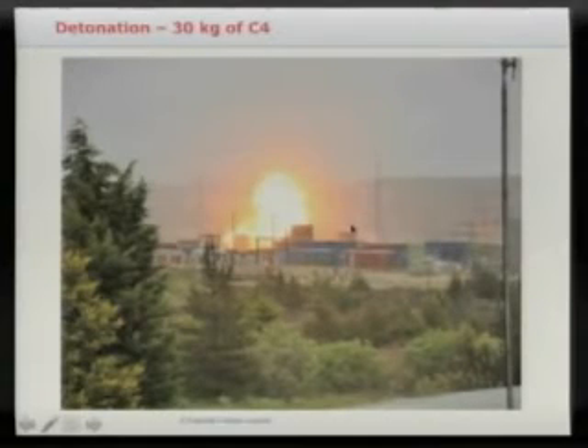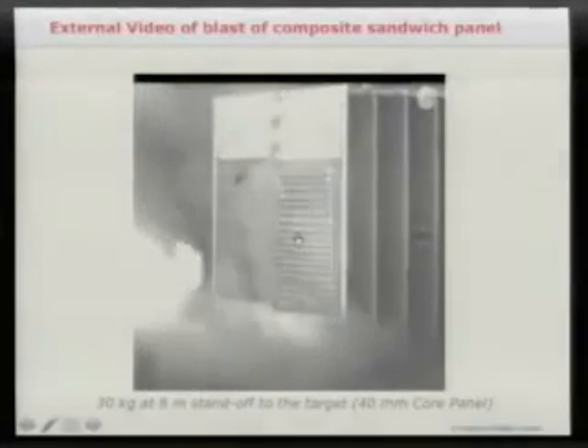So that's the charge going off from a safe distance. And now you're close in. This is the video of the front of the panel. So you'll see, this is the worst-case scenario. So this is when the charge is very close. You'll see the fireball from the charge. And it's probably too quick to see the crack, so I'll go back and do that one again. If you look now closely down this left-hand edge, you should just see the crack propagating down that left-hand edge. That left-hand edge is not so well supported, and that's why the crack initiates there.